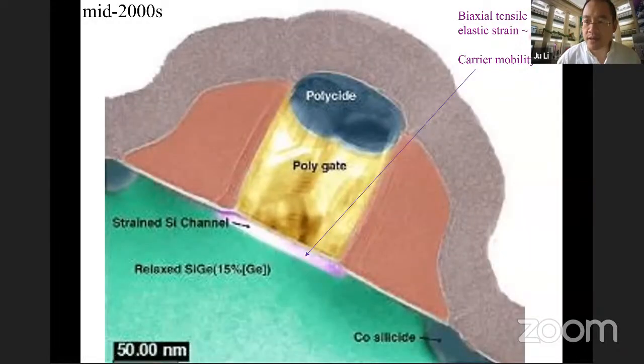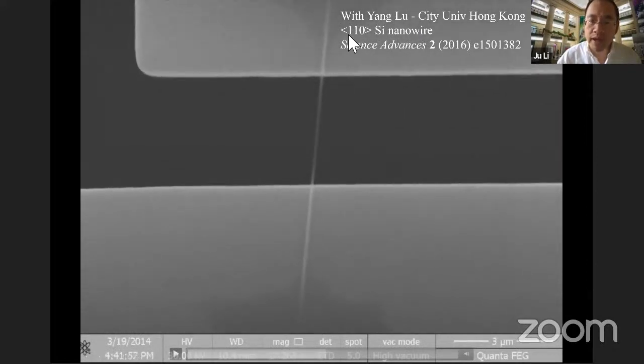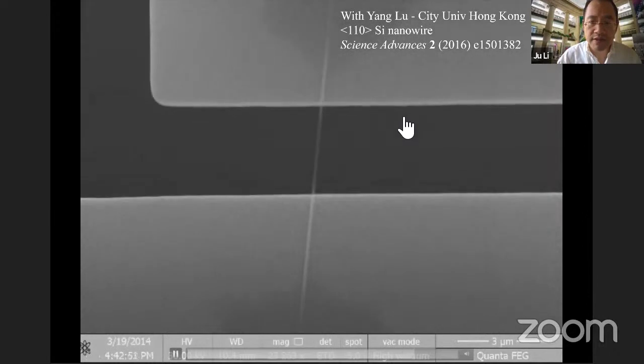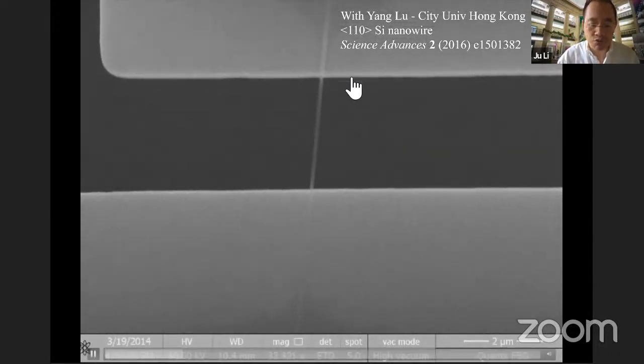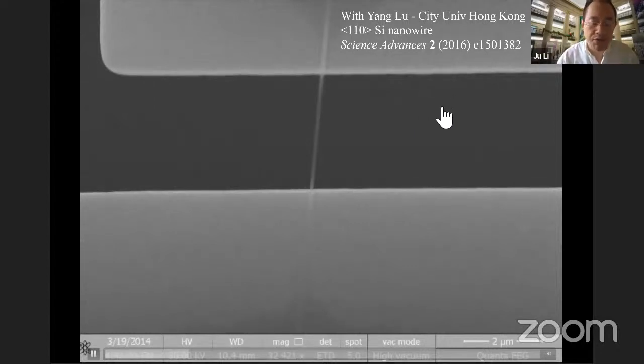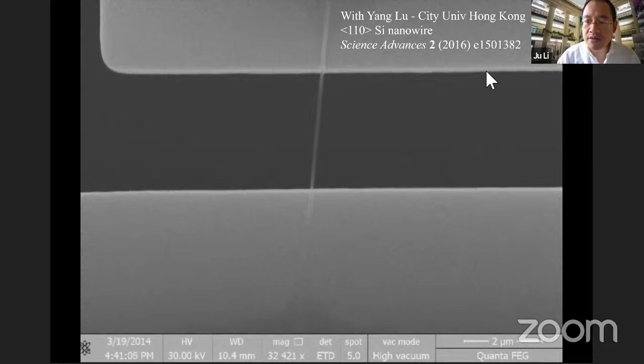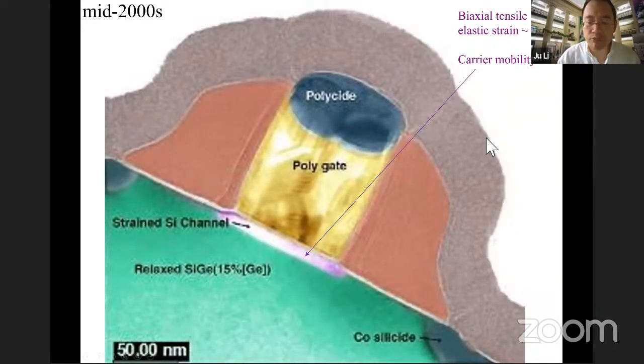However, what we are right now driving is way bigger than 1% tensile strain. So what we try to do is 5%, 10% elastic strain in so-called deep elastic strain engineering. And this is in collaboration with Professor Yang Lu at City University of Hong Kong, where we have a silicon 110 nanowire that is glued to a MEMS device. And we found that it can be strained to 13, 14, 15% tensile strain, and it's very reversible until toward the end, it fractures. But before that, it's really elastic and reversible deformation. So a natural question is, with 15% strain, 15 times bigger than what we are using industrially, what can the physical property be?